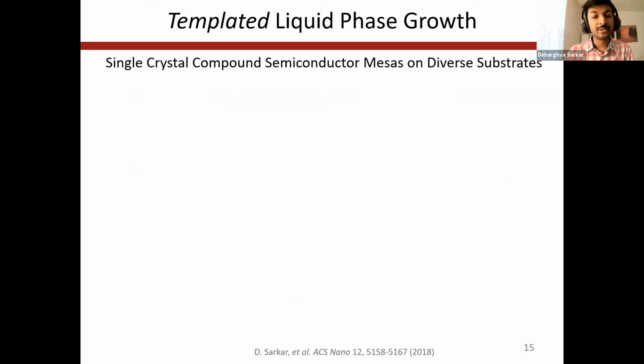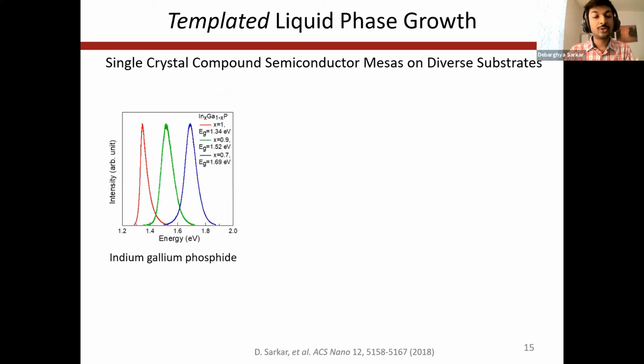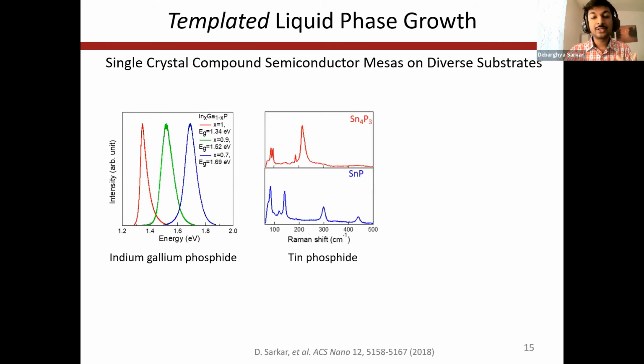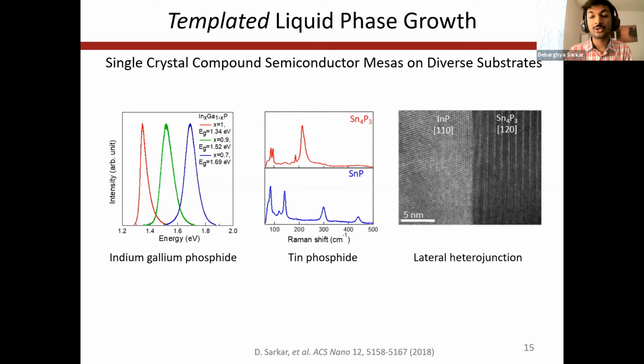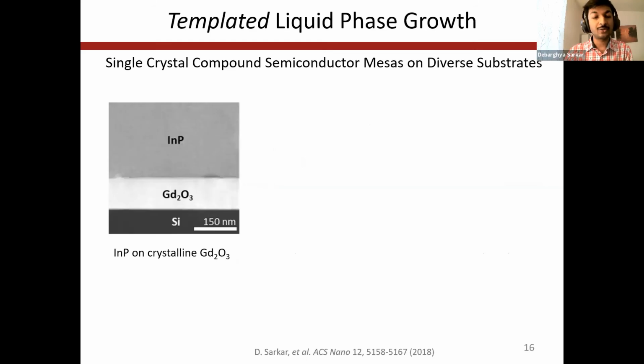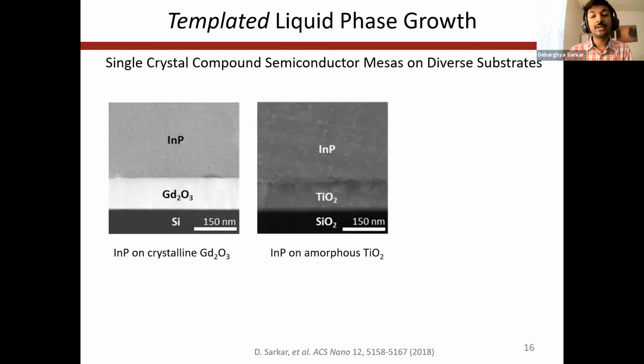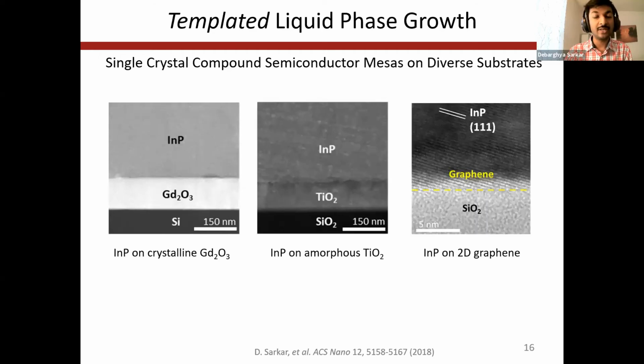And some specific examples from there, these show different stoichiometries of indium gallium phosphide, stoichiometry controlled tin phosphide, as well as a lateral heterojunction between indium phosphide and tin phosphide. Also, growth on different substrates, such as growth of indium phosphide on crystalline gadolinium oxide, on amorphous titanium oxide, and on two-dimensional graphene transferred on silicon oxide.